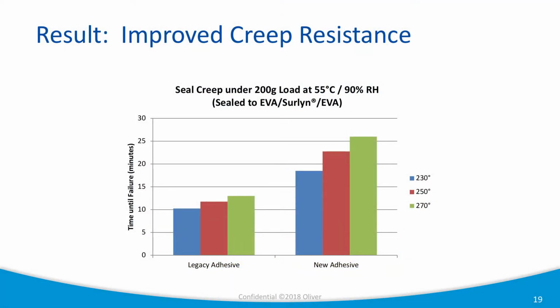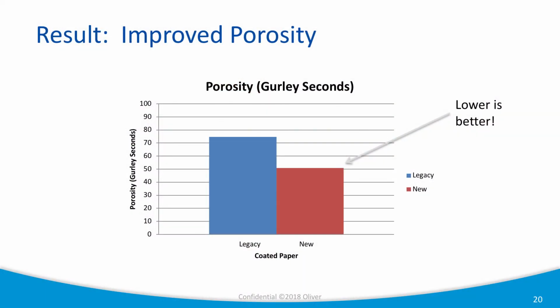You can see that graph-wise. Here we have on the left side the time until failure, so that would be the time for those weights to drop off, at three different seal conditions: 230, 250, 270. You see the legacy adhesive was dropping off in the order of 10 minutes, and this reformulated version basically doubled that, so a significant improvement. And also with that formulation, we were able to get improved creep resistance, or improved strength, as well.